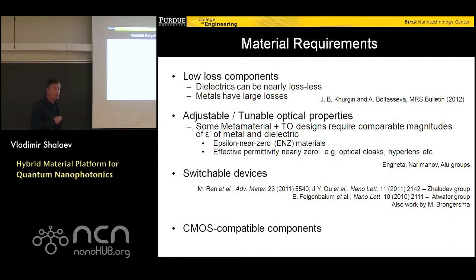The real part of the electric permittivity, as I mentioned, at telecom is actually huge, like -100, which is sometimes not good, particularly for realizing so-called epsilon-near-zero materials, where you would like to take advantage of materials where epsilon is close to zero. I already mentioned that you could have this fantastic opportunity to switch materials when epsilon is close to zero. And if you would like to accomplish this, epsilon close to zero, or let's say -1 or +1, you quite often mix metal with some other material.